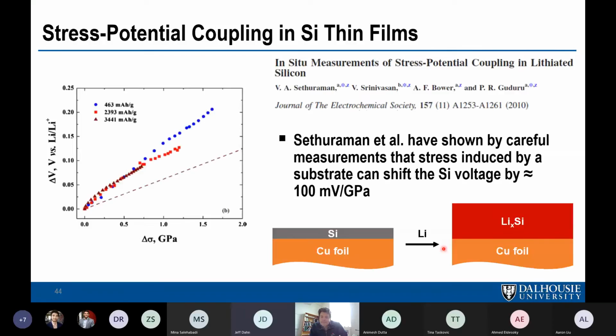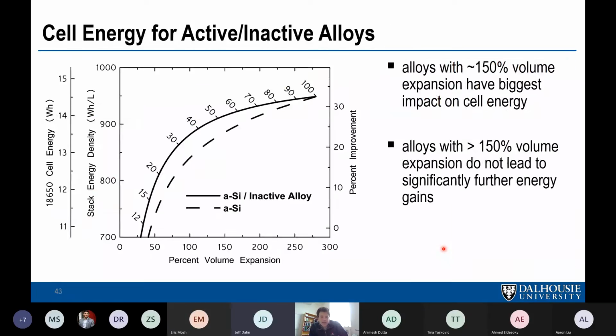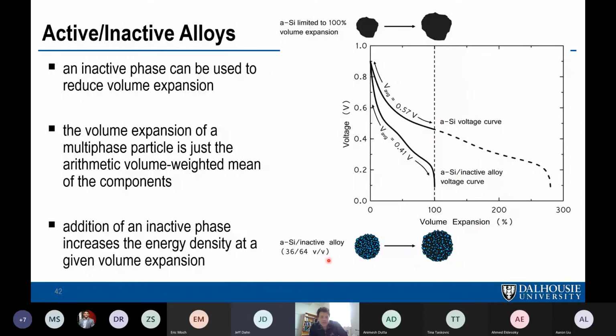Hey, Mark, why do you say you have to have a percolating silicon network? Don't you just have to have a conductive matrix? The inactive phase doesn't conduct lithium. This is for alloy materials. If you have something like SiO, then the inactive phase is an ion conductor. Got it. But even in SiO, this would be a correct model. This discussion is right now restricted to alloys, where this would be maybe iron silicide, something like that. Got it, thanks.